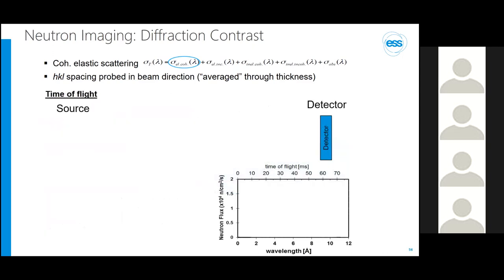I'd like to take this opportunity to also talk briefly about time of flight, what we typically do at spallation sources. This wavelength selection that I've just shown can be done by a monochromator, which is typically done at a neutron reactor source. At a spallation source, one typically exploits a time of flight technique, so I will briefly explain the principle here. Let's not yet place the sample in front of the detector. Neutrons of all wavelengths start at the origin at time zero, so lambda one and lambda two, and then they travel towards the detector and are separated by their velocity. Neutrons of short wavelengths arrive first and those with long wavelengths arrive later. The detector then records the incident neutron spectrum of your neutron source that you can see here.